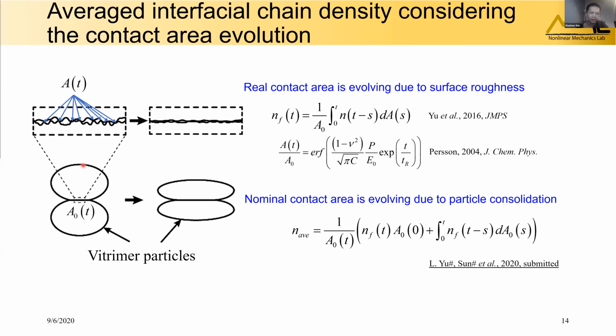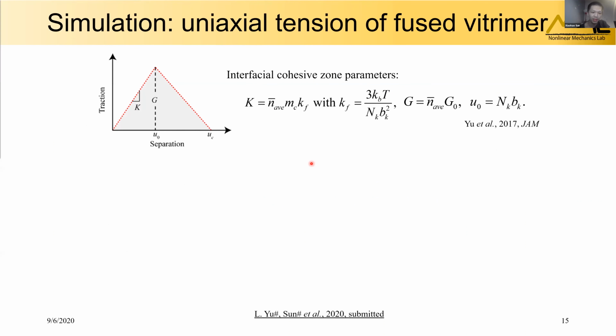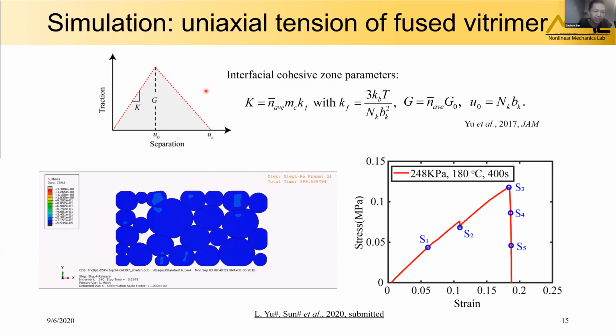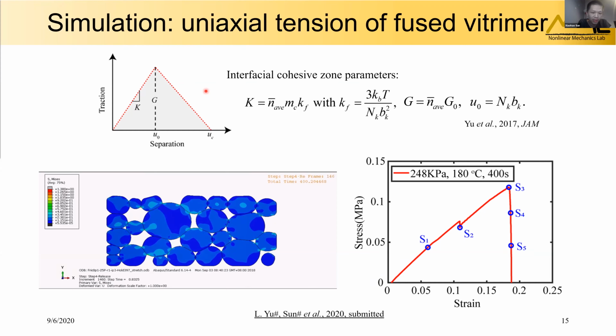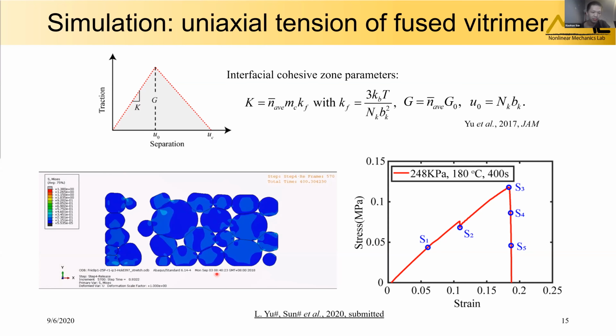And in the macro scale, during the heat press, the nominal contact area A0 can also evolve. So to consider this effect, we use a similar strategy and obtain this average chain density for each contact interface between the particles. And once we have the chain density at the interface, we can determine the cohesive zone model. Then we can simulate the uniaxial tension process. Here we can extract the effective stress strain curves and calculate the modulus and the strength from the curve. We can see the particle system has been broken.